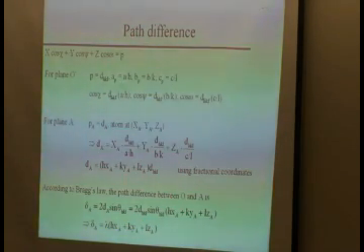So we can replace this thing with lambda. So our phase difference, our path difference, is actually lambda times hxa plus kya plus lza. Who would have thought that it would become such a simple expression when we started a slide ago? As I said, sometimes knowing where you're going really helps, okay? So, that's our path difference.